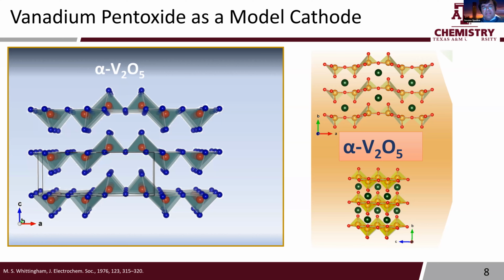And the reason, you can see why it's so attractive. It's got this sort of layered framework, lots of open sites in between for lithium ions to be accommodated. And then you've got this vanadium 5+, which can be readily reduced to 4+ and 3+. And so there's clearly a lot of room to store lithium ions through redox chemistry. Okay, and you can see this here where you've got some of the sites for lithium ion storage delineated.